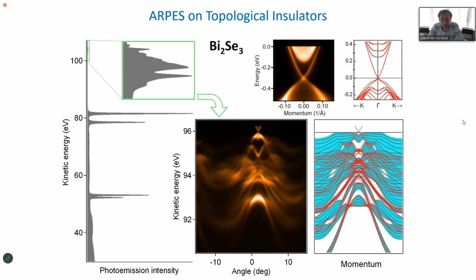and a brief introduction to ARPES, angle-resolved photoemission spectroscopy, which allows you to see the electronic structure. So this is exactly what I call the electronic structure, and this is a distribution. You can consider it as a distribution of the fermionic spectral function in the occupied part of the band structure, right? And it is easy to measure, because the experiment is a simple photoeffect. If you shine the material with photons of fixed energy, and you analyze the photoelectrons, then you analyze their energy and angular distribution.